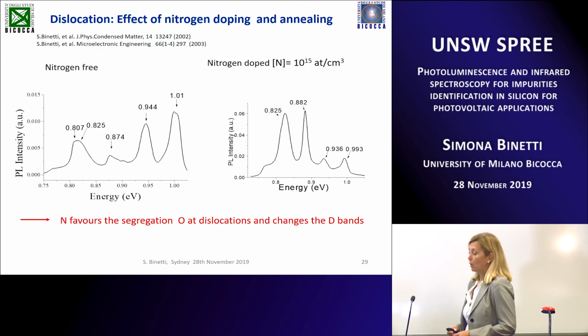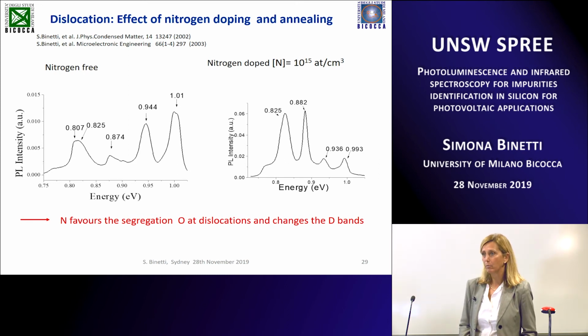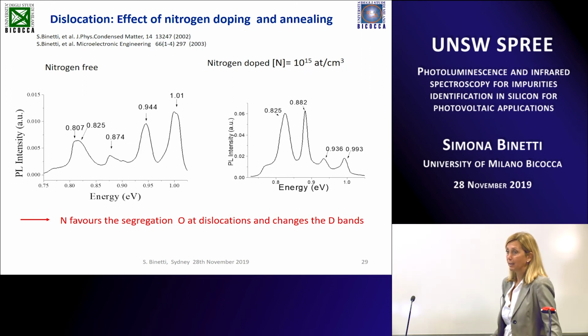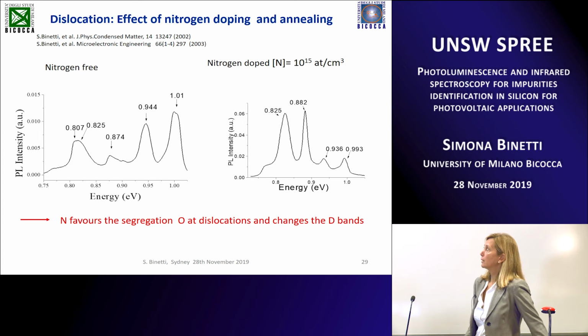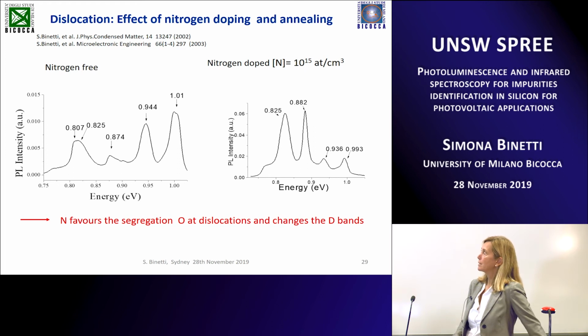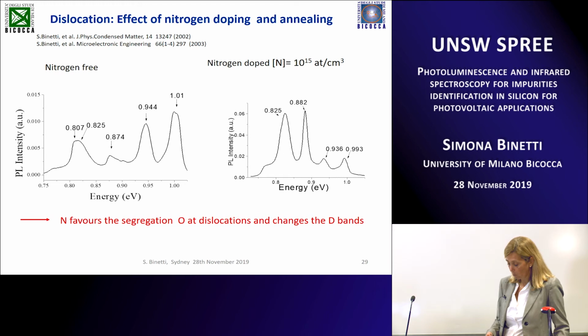This has been proved, for instance, also by studying the combination with other impurities that you can have in your samples. Nitrogen. Nitrogen is much more common in silicon for microelectronics, because it was introduced in order to increase the mechanical stability of the Czochralski silicon. And you can see that if you perform plastic deformation in nitrogen-free Czochralski silicon, you have the D1, D2, D3, D4 lines, and if you perform the same plastic deformation in nitrogen-doped silicon, you can see that we have a completely different shape around D1, because due to the fact that nitrogen increases the segregation of oxygen at dislocations, we have a change in the D-band position, and the emission light is related only to oxygen precipitates, and the D1 is not visible anymore.